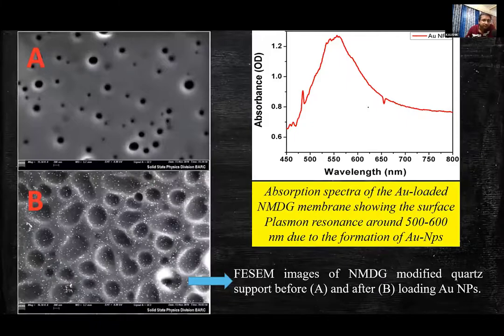Now, this is the absorption spectra of that gold-loaded NMDG membrane. As you can see, there is a sharp peak at around 500 to 600 nanometers, which shows the presence of gold nanoparticles, because this sharp peak arises due to the surface plasmon resonance occurring due to the formation of gold nanoparticles.